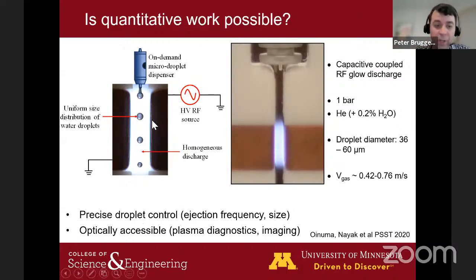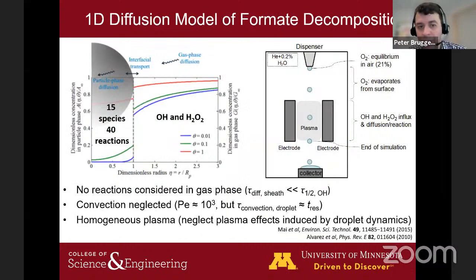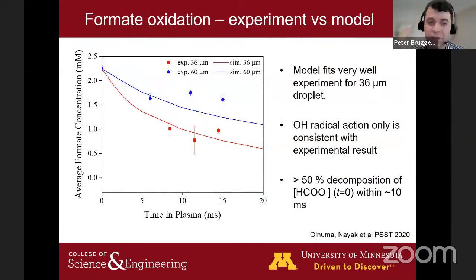And interestingly, these droplets are water. They go through a plasma. The residence time is maybe 5 to 10 milliseconds. And they are not evaporating much. Okay, so we're working at very low temperature conditions where we can send droplets through the plasma. They are charging. We give them sufficient momentum so they can transfer through the plasma. And so, without going into much detail, we've been measuring the conversion. We've been modeling that process.